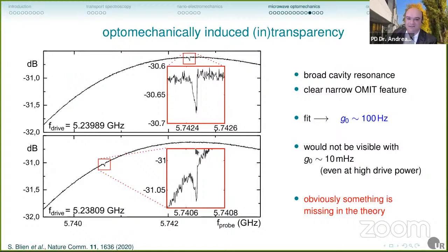Can we see that? Amazingly, we can. The large line here is the cavity resonance, and this tiny dip here is the coupling with the mechanics. This is our mechanical resonance of the carbon nanotube. And we can fit this and obtain a coupling parameter of 100 Hertz. And that is 10 to the power of 4 larger than the 10 millihertz that we obtained with the simple theory estimate. If we had really 10 millihertz here, we wouldn't see anything. We would just see the big cavity resonance, nothing else. So obviously in this theory from the aluminum beam, something important is missing.